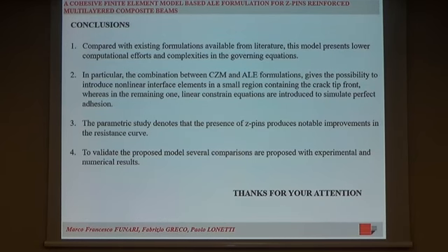To conclude, compared with existing formulations available from literature, this model presents lower computational effort and complexity in the governing equations. In particular, the combination between cohesive zone methodology and ALE formulation gives the possibility to introduce nonlinear interface elements in a small region containing the crack tip front, whereas in the remaining one, linear constraint equations are introduced to simulate perfect adhesion. The parametric study denotes that the presence of Z-pins produces notable improvements in the resistance curve. To validate the proposed model, several comparisons are proposed with experimental and numerical results.